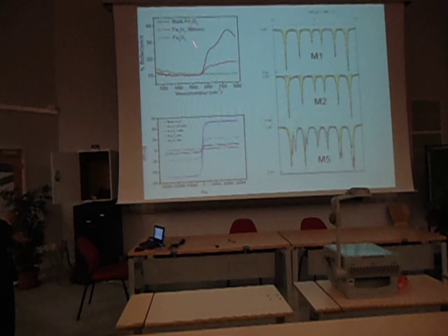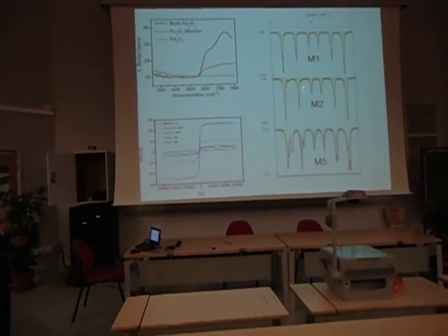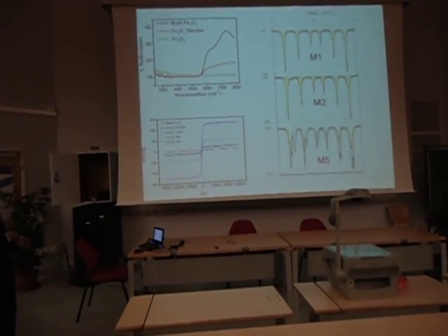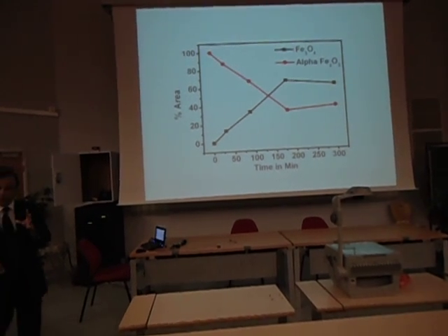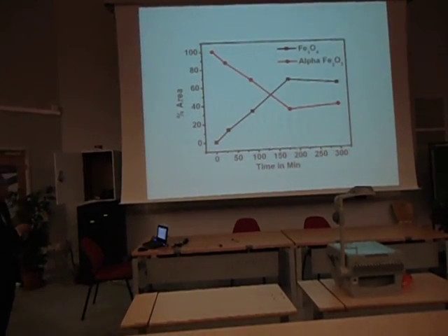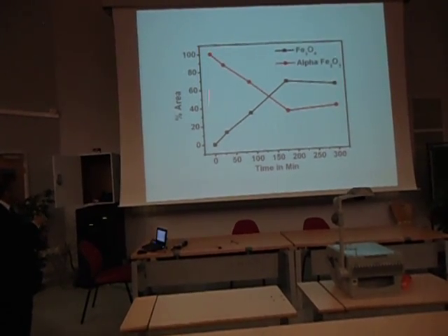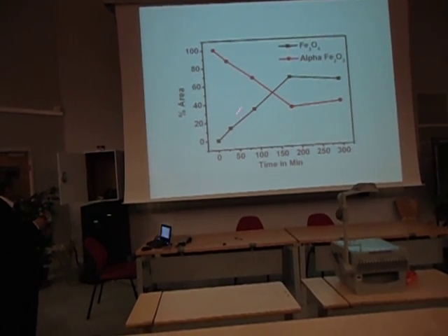Interestingly, if you look at various properties there, the magnetism and so on, we see that the Mossbauer spectra evolve in this particular way. What we find from the relative contributions is that we are actually getting a mixed configuration between Fe2O3 and Fe3O4. Initially we start with Fe2O3, no Fe3O4, but as you keep on blasting with the laser, we get a mixture of both.